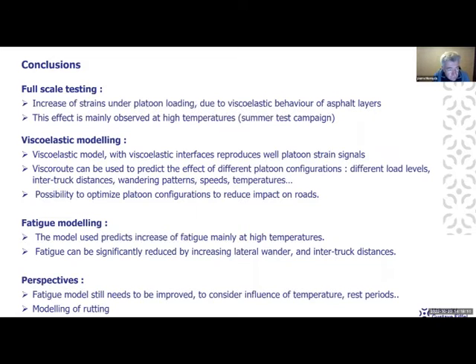So from the full-scale testing, we found that there is a significant increase of strains under platoon loading due to the viscoelastic behavior of asphalt layers. And this effect is mainly observed at high temperatures, when the behavior of the pavement is strongly viscoelastic. Then with the viscoelastic model, we found that a model with viscoelastic layers and viscoelastic interfaces reproduces well the platoon strain signals. And we were able to use this model to predict different platoon configurations and possibly to optimize platoon configurations to reduce impact on roads or to reduce maximum strains.